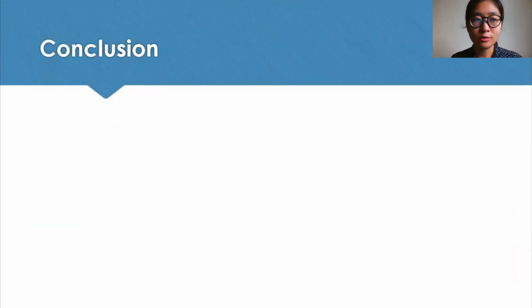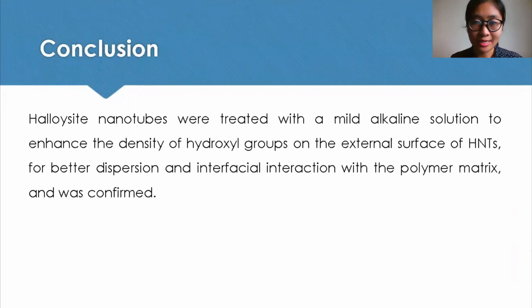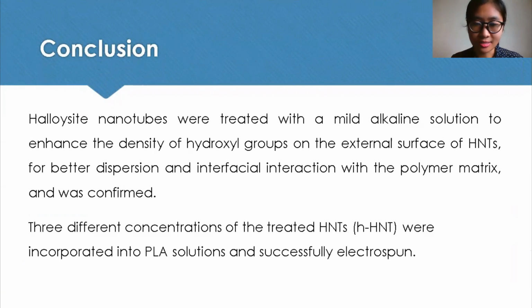In conclusion, halloysite nanotubes were treated with a mild alkaline solution to enhance the density of hydroxyl groups on the external surface of HNTs for better dispersion and interfacial interaction with the polymer matrix, and this was confirmed. Three different concentrations of the treated HNTs were incorporated into PLA solutions and successfully electrospun.